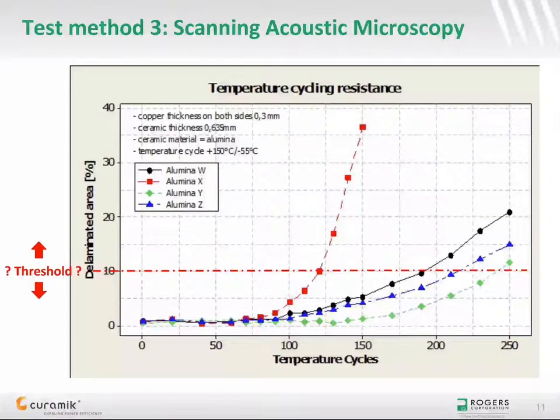The most promising approach to define the progress of a degradation is to measure the delaminated copper area as a percentage of the total metallization area. This requires a very good and consistent resolution of the image. Note that the resolution of the image is limited either by the physical scanning resolution or the frequency of the sound. This also requires adequate equipment and software for image analysis.